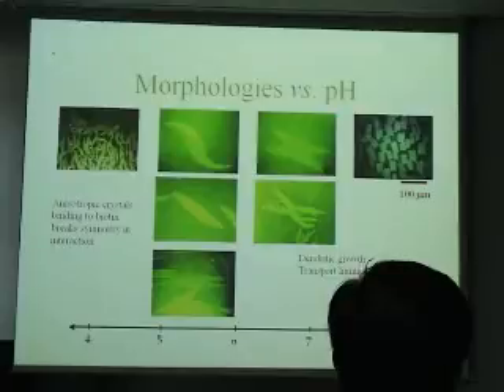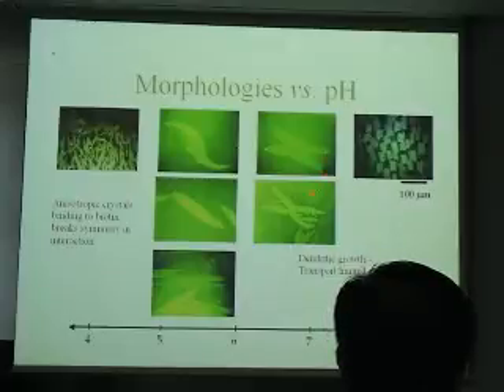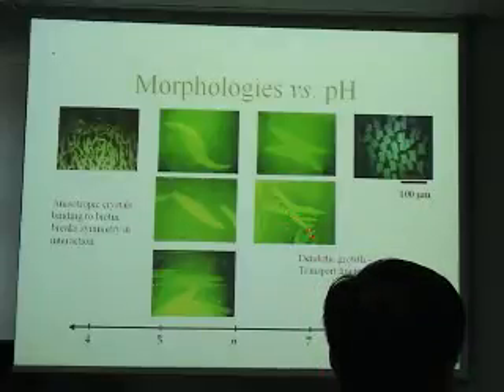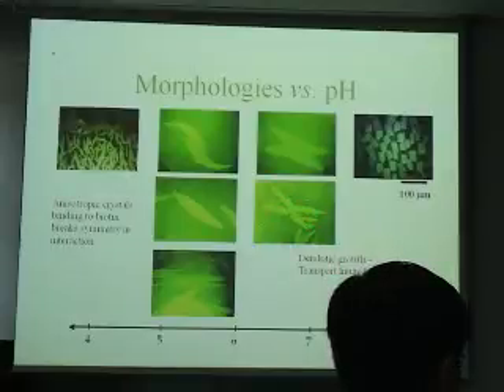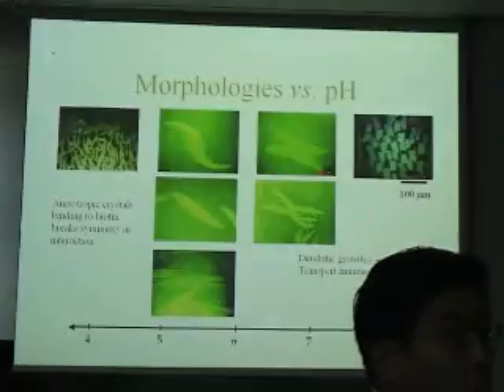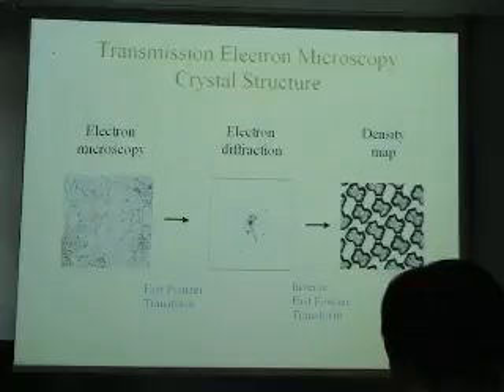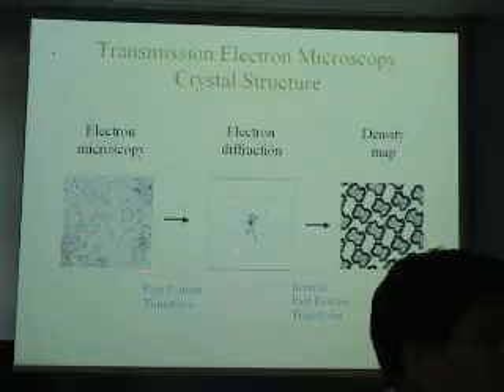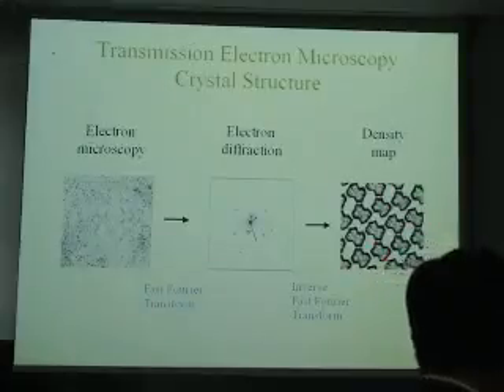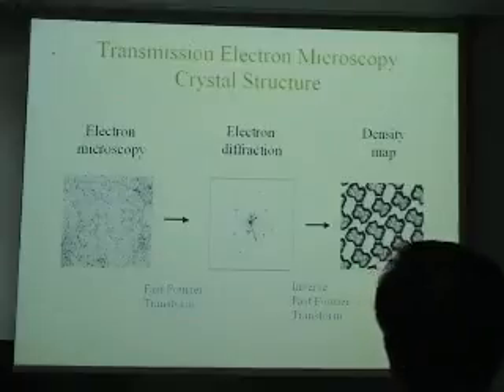I didn't want to go through all that here, just to tell you that it shows you how weak the forces are and how delicate they are, that the binding actually gives you a change in the energy for the crystallization and gives you anisotropic crystals. You also get these dendritic growth patterns because we have transport-limited crystallization. The streptavidin has to diffuse through the avidin, and you get a concentration gradient set up, much like you have a temperature gradient in a snowflake. In any case, we found we could get these different morphologies, and indeed, we do the electron microscopy, electron diffraction, and then determine density maps for the proteins. And these are done with a stain, so they're not very high resolution, but they're good enough to determine the structure that we need.